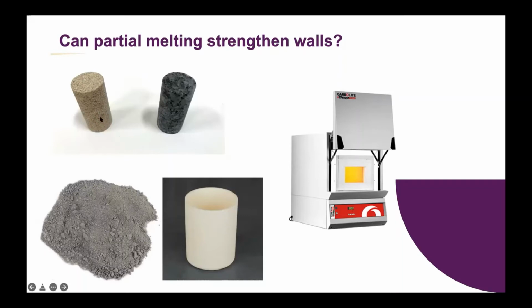So we did two types of experiment. First, we took some sandstone and some granodiorite, and we cored them and we heated them up for different temperatures and different times. And then we measured the strength of those materials after exposure to high temperatures. And we also crushed the same materials into a powder of different sizes and loaded those into crucibles and exposed them to the same temperatures and times and measured the strength of those materials afterwards as well. This is sort of replicating the clasts in these walls, and this powder is replicating the material between the clasts that we think might be responsible for holding together the clasts after vitrification.